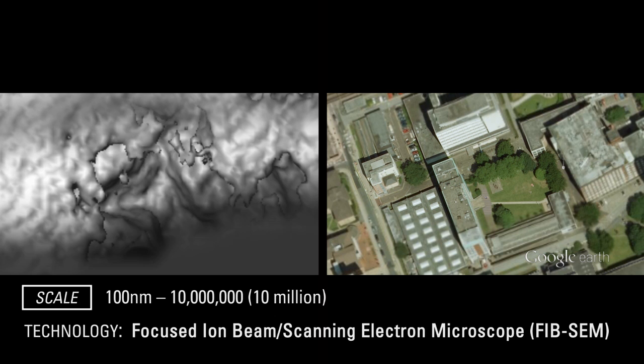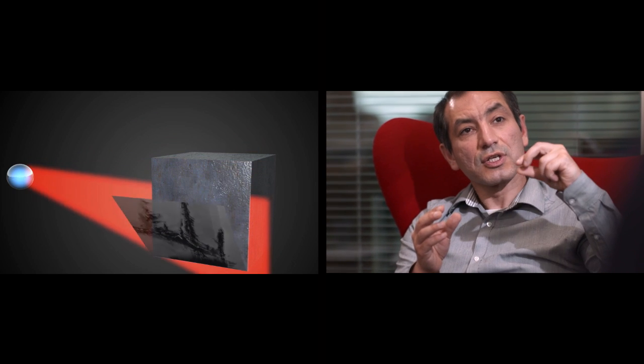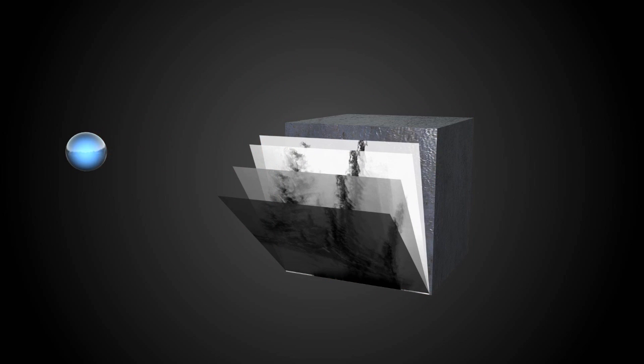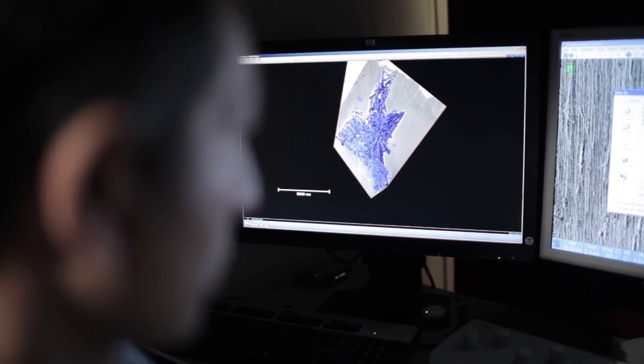We then need to use electron microscopy techniques to look at high resolution at those sites. In the next step, we move in another 100 times to the 100 nanometre scale. The key scale of 10 to 100 nanometres in scanning electron microscopy allows us to look at the grain boundaries in the microstructure involved in this corrosion activity. We use a focused ion beam to eject atoms from the sample surface and cut the sample in successive nanometre-resolution slices, which we compile to make a 3D reconstruction. The 3D reconstruction allows us to see the microstructure in context with the corrosion, and to see which boundaries are corroding and which are not.